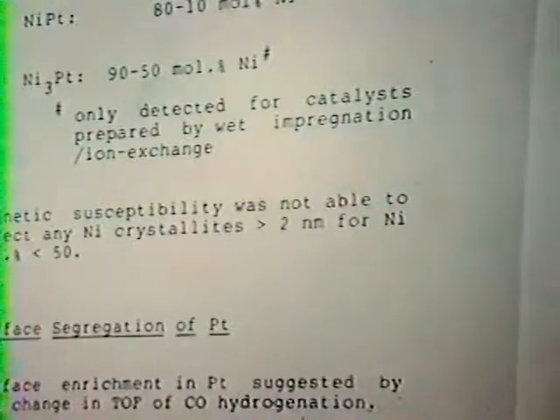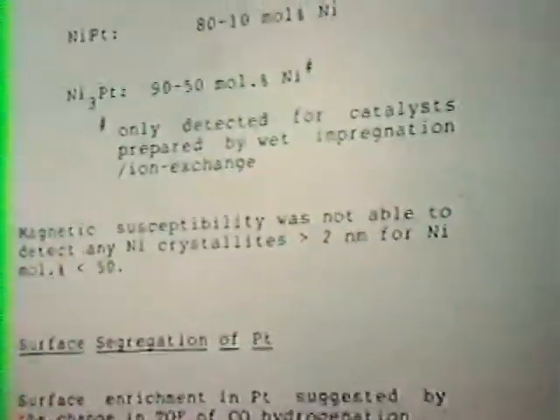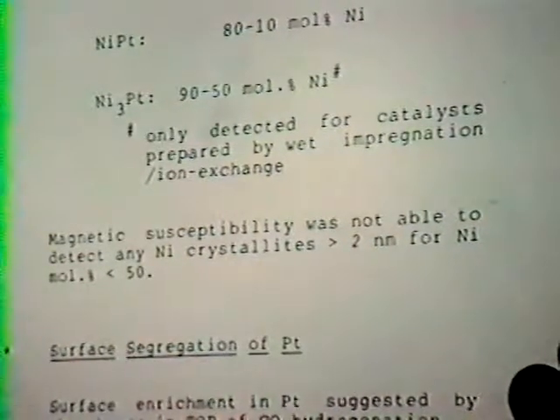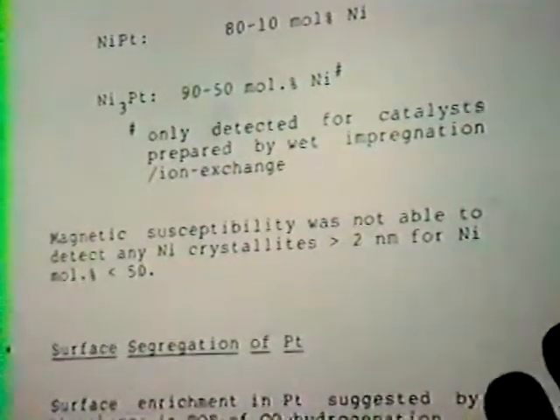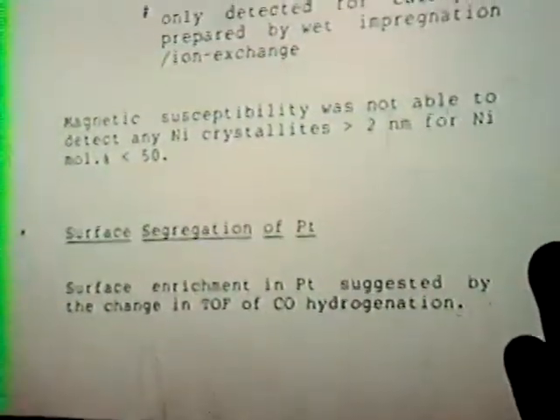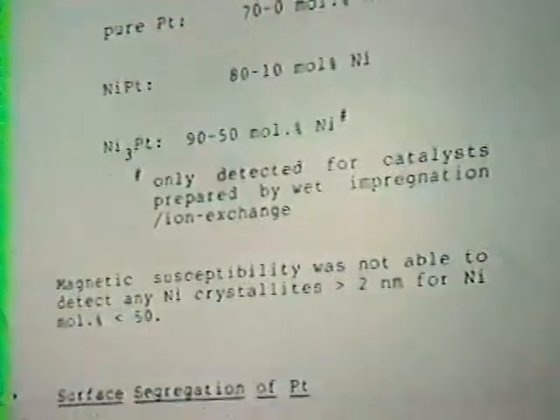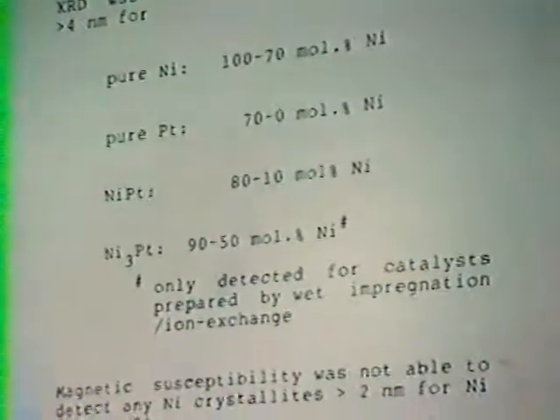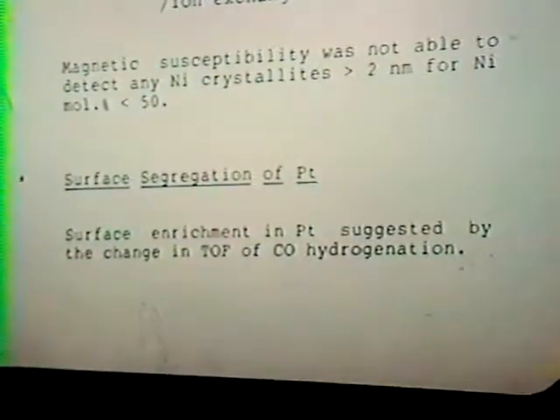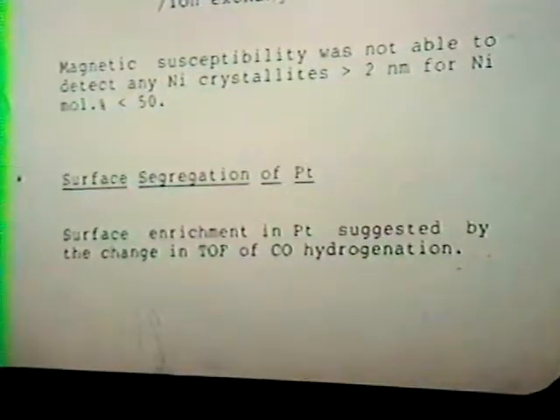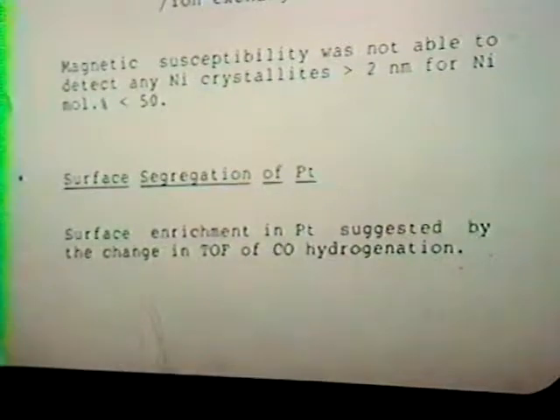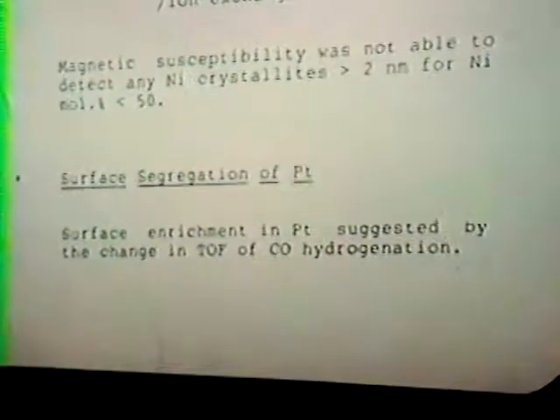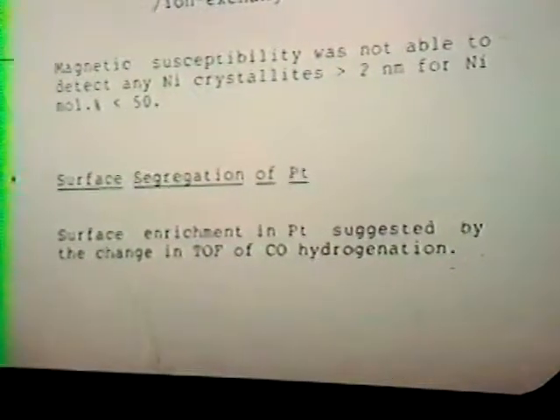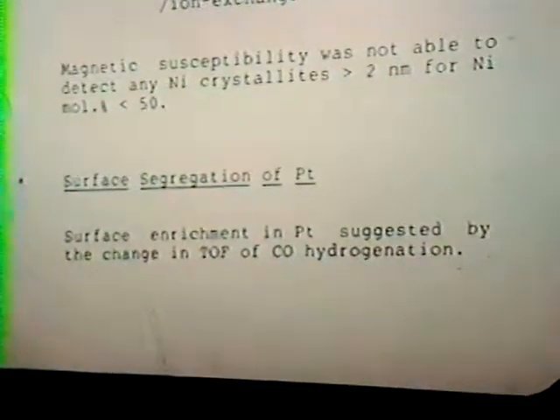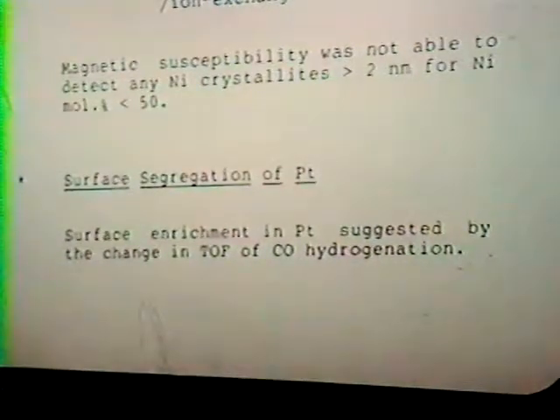Obviously, I'm sure, without a temperature program, you could reduce it over some hours at the lower temperature. XRD indicates that there's certainly pure nickel phases present at the high concentrations of nickel. There's certainly pure platinum phases over quite a wide range of the system. And we do have definite alloy formation between the nickel and platinum. There is surface segregation of the platinum, which suggests that if one is trying to achieve the catalytic properties of the base metal, perhaps you would want to concentrate on something which does not segregate to the surface, because obviously you're getting less and less of the nickel surface character in these systems.